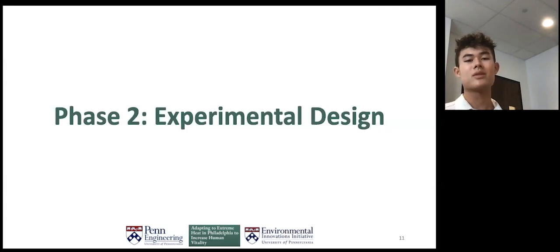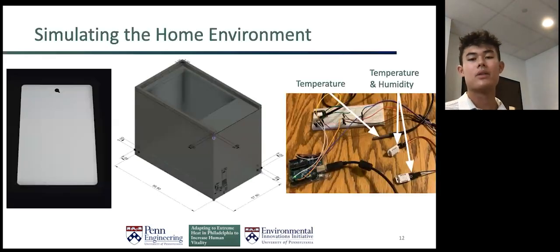And then the next step in my summer project was developing an apparatus that we could use to test our own coatings that we'll eventually make in-house. The goal with this was to make an enclosure that could simulate the conditions inside a real house as it's exposed to sunlight. And we did this with the 3D printed box that you see in the middle. So this is made of ASA plastic in white because ASA has a relatively high glass transition temperature, 85 degrees Celsius, which is enough for our purposes. And then the white color is so we can hopefully isolate the effect of different roof coatings and reflect most of the light that actually hits the box.